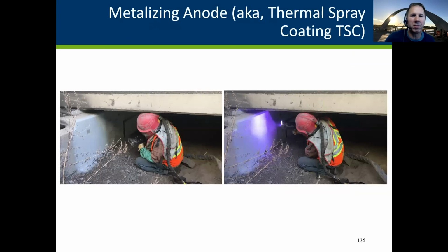So that is one form of anode. There's also an external anode. Just like a paintbrush, they spray it on the surface, and they're spraying the surface with molten zinc or molten metal that then gives itself up instead of the steel inside the concrete starting to corrode. So just like you galvanize your bumper or whatever, you're putting a metal that wants to corrode faster than the metal you're covering. But in this case, the electrical action happens through the concrete.